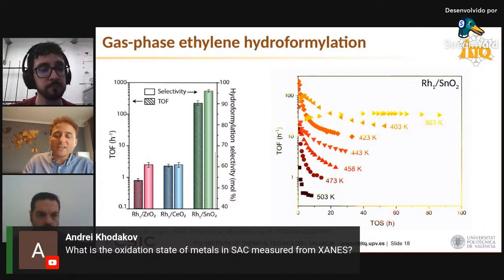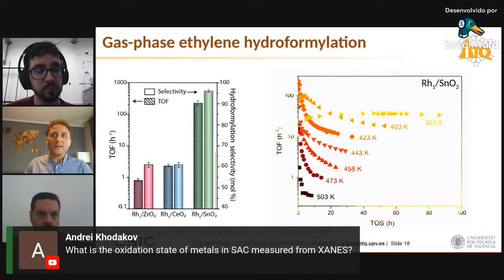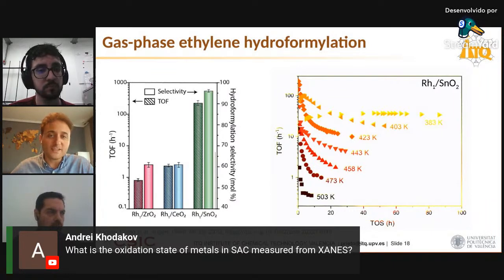As prepared, as soon as they have been prepared by this high temperature oxidative redispersion and trapping, and before we use them, so before we expose them to hydroformylation conditions, the oxidation state is 3-4+. It is very difficult to differentiate between those two oxidation states for rhodium, even using XPS. So we actually assume it's 4+, and rhodium is isomorphically substituting tin 4+ on tin oxide.